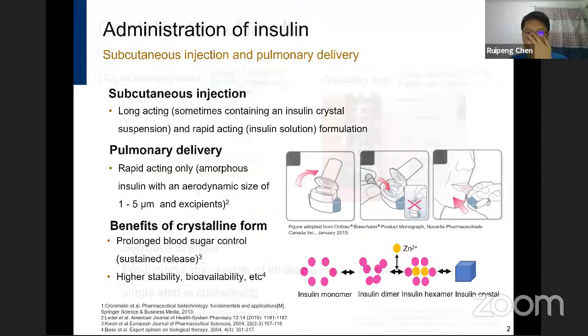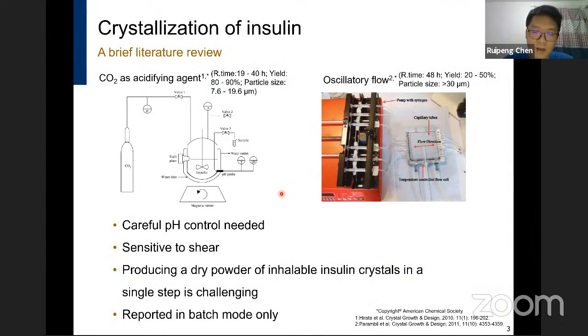Since insulin was first crystallized in the 1920s, it has been studied for various purposes, for example, to get high quality single crystal X-ray data by growing large crystals. And here we want to make general conclusions regarding insulin crystallization. So first, careful pH control is needed because the solubility of insulin is sensitive to the pH. As reported in this paper, they used carbon dioxide as the acidifying agent to adjust pH and then create supersaturation.